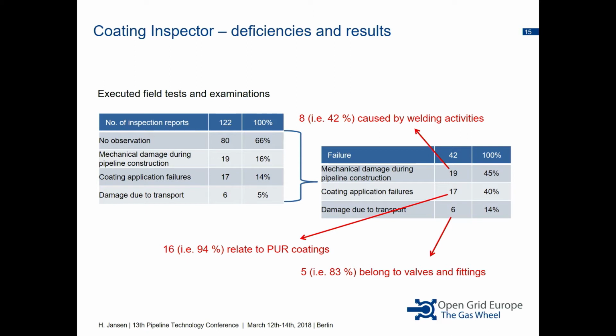So if you take these 42 things that are here, a total number of 42 test reports, then you can say these 19, half of these were caused by welding activities. The welders put their welding equipment like brushes and welding machines on top of the pipeline and destroyed the PE coating.